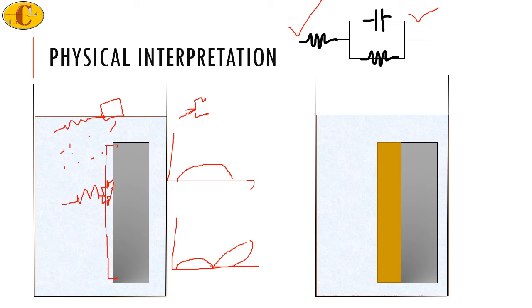So in that case, you may only see a single semicircle. As the time goes and the inhibitor starts degrading, you may again see the development of the second semicircle. So the second semicircle in this case indicates that now the inhibitor film is not good enough and the metal has started contributing to the corrosive action. So the second circuit will now come into play. So depending on the actual physical conditions, you have to decide which circuit is right for you and then go with the fitting after that.